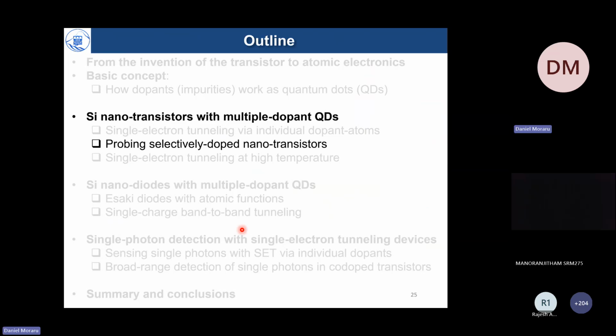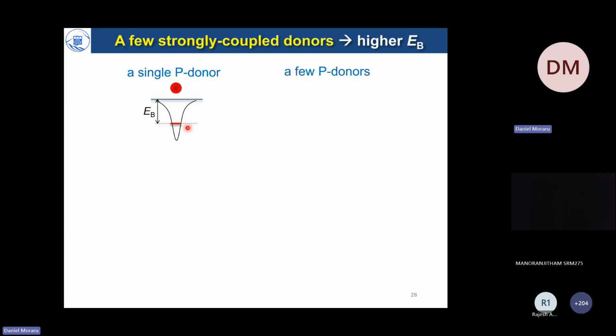Later, we realized that there is a little bit of end of the line for these single dopant devices because it's very hard to control single dopants. We therefore introduced a selective doping technique that allows us to build not single phosphorus donors as quantum dots, but to couple a few phosphorus donors, strongly or less strongly, as a new quantum dot.